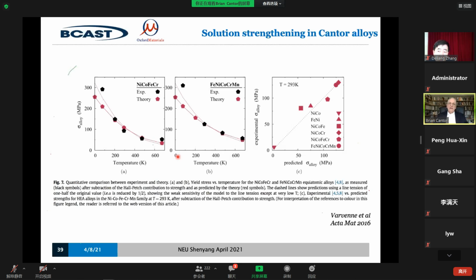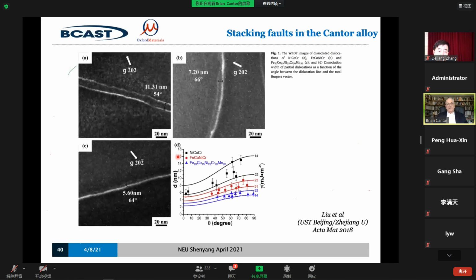And if you look at the dislocations, there are two effects I want to show you, looking at the dislocation in more detail. These are the wiggly dislocations that I showed you, caused by the local lattice strains. We can see the deviation of the dislocations caused by the local lattice strains. In fact, if we go to high resolution electron microscopy, that's one way of measuring the local lattice strain, because you can actually see the deviation of the planes of atoms.